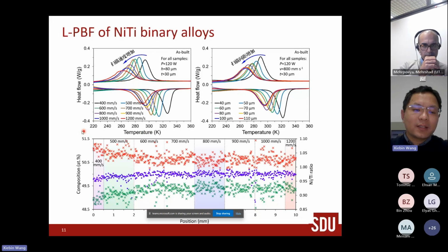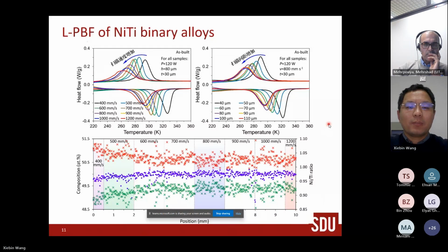The mechanism underneath this phenomenon is quite clear, because if you lower the energy input, you lower the nickel loss by evaporation. So lower nickel evaporation leads to a higher nickel content in the matrix, and then a lower martensite transformation temperature. The very important aspect of this result is that if you want to tailor the transformation temperature, you have to control the nickel content very precisely, like 0.01%. But with LPBF, you can just change the scanning speed. It's very easy to modify the scanning speed, and then to tailor the transformation temperatures.